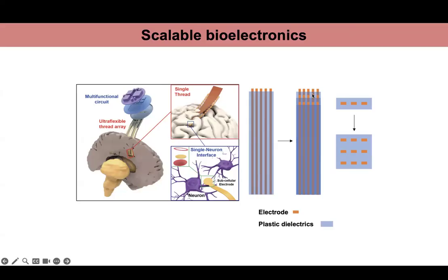As a result, if you scale up the number of sensors that you can incorporate into those brain probes, essentially you need to incorporate a large amount of dielectric material that makes the entire probe thicker again and become rigid. And all those issues, the immune response, foreign body effect, the mechanical drift will come back.